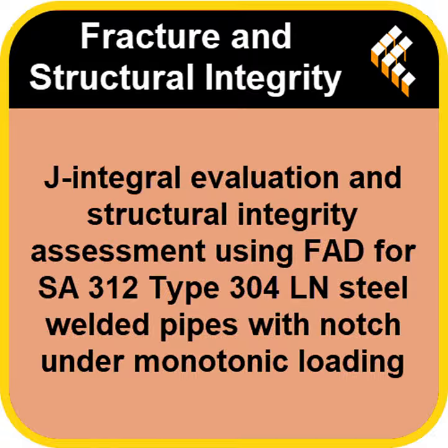how resistant is it to that crack growing? That's a great analogy, actually. KR is the ratio of the applied stress intensity factor, that's the K, the actual measure of the stress concentrating right at the crack tip, to the material's inherent fracture toughness. Fracture toughness is like its ability to absorb energy. Exactly. Its ability to absorb energy before that crack begins to spread uncontrollably, possibly very rapidly. So a high KR means the stress at the crack tip is getting dangerously close to what the material can handle.